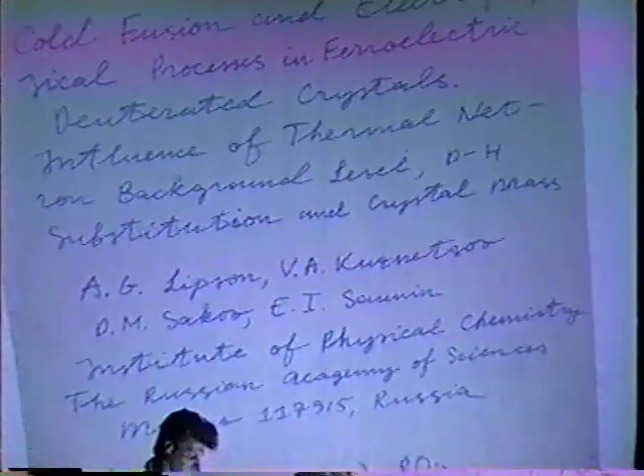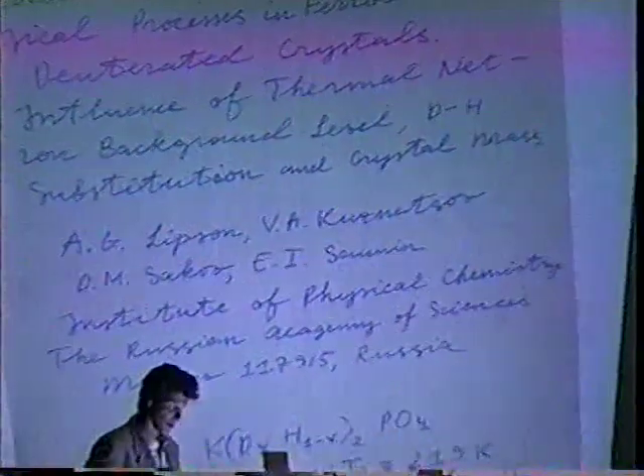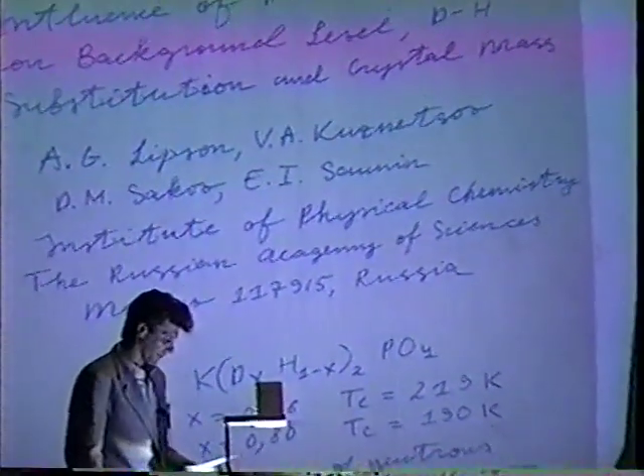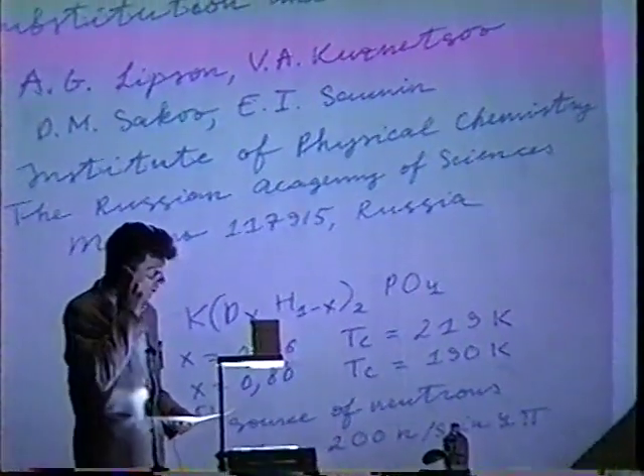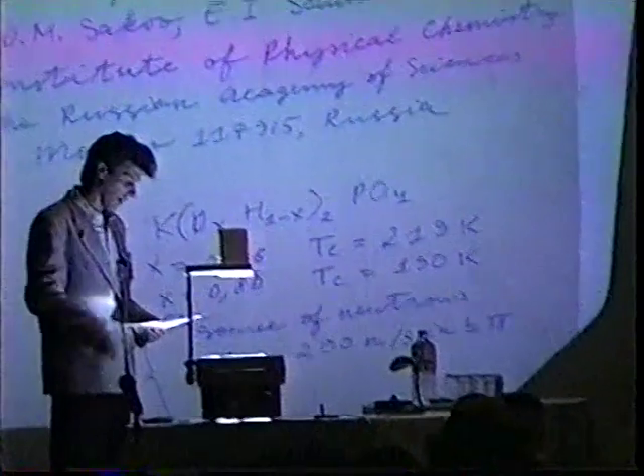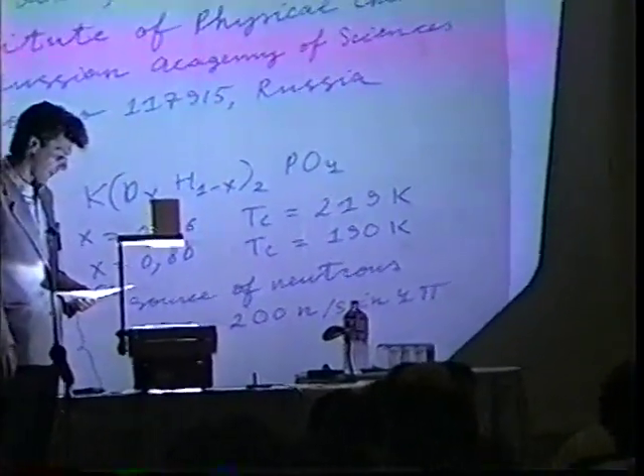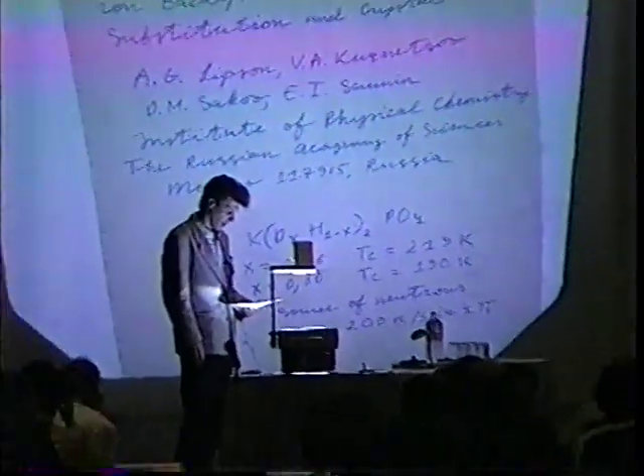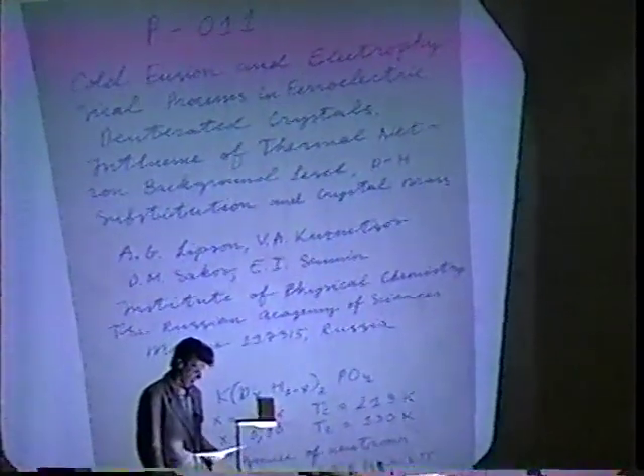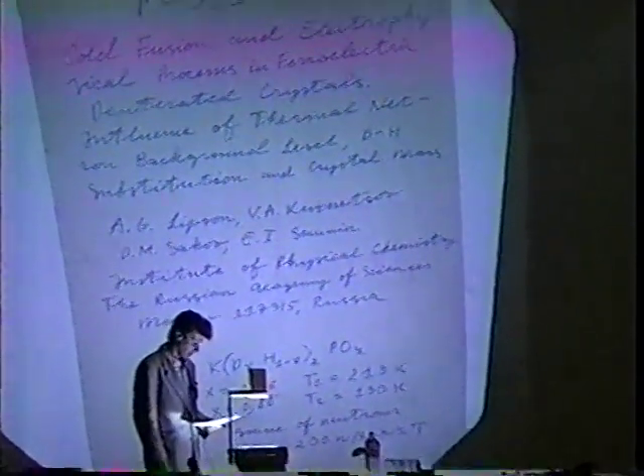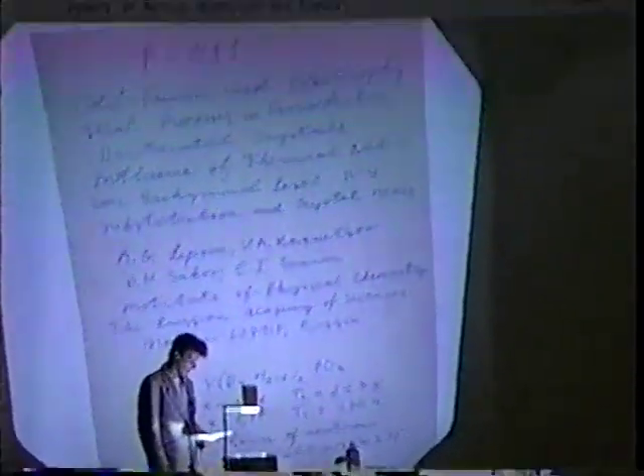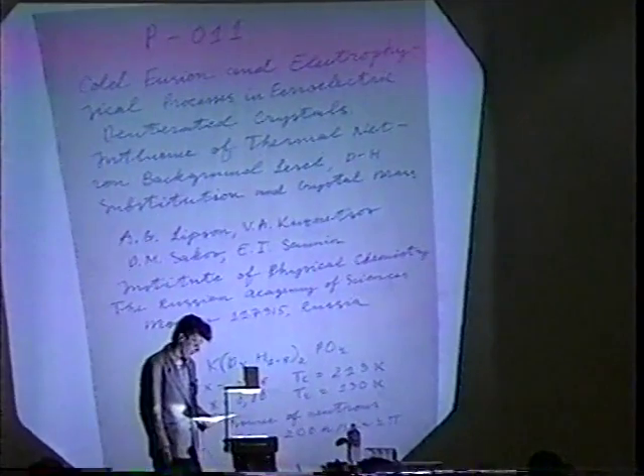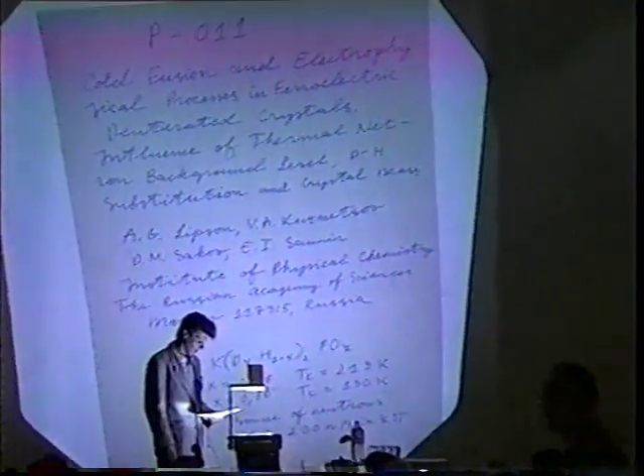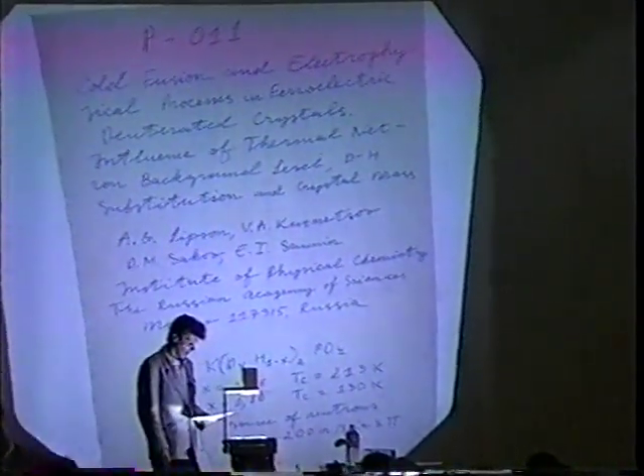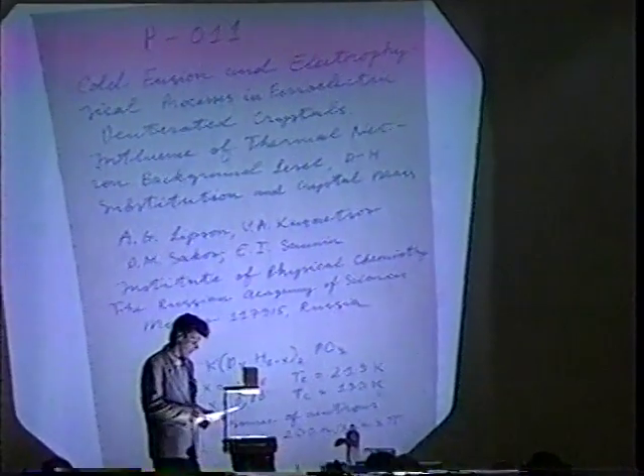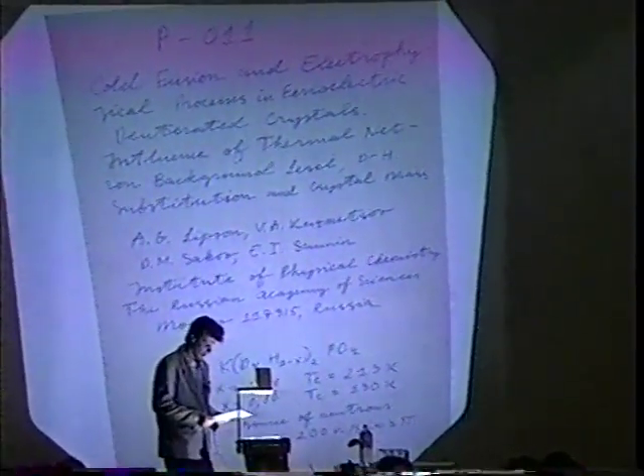As was shown earlier by us, on the transition through the Curie point in DKDP crystals with deuteration degree 96 and 80%, under conditions of external thermal neutron background radiation, the excess emission of fast neutrons is observed. In the common case, there may be amplification or attenuation of the external thermal neutron flux passing through the crystal in the vicinity of the Curie point. As a result, emission of neutrons in these crystals can get a positive or negative sign with subtraction of the background.